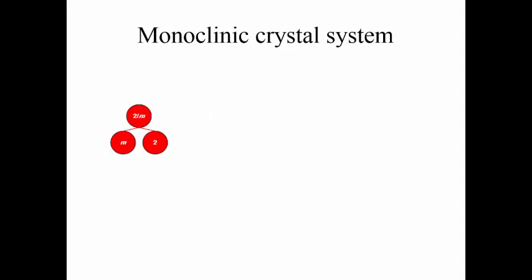Now, half of you are monoclinic people. So here you're going to have your 2 over m. Here's your monoclinic, and you can see how there's a contribution from the mirror to the 2 over m, a contribution from the 2, and we join them together, and that generates an inversion point right in the middle here. You can see this red goes to the blue, and the red on the top here goes to the blue on the bottom. Notice that this bullseye that I keep talking about indicates that we're going to have a mirror plane in the plane of the computer, the plane of the paper.